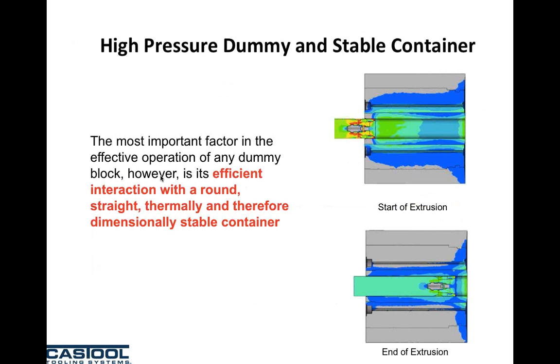What we are trying to achieve, through a high pressure dummy block and a stable container bore, is an efficient interaction of the container, liner, and dummy block. So when you start to push, the active clearance between the liner bore and the dummy block is consistent, and when you retract, the dummy block is not yielding and the nominal stays the same, so you can retract and leave the skin, not touching or dragging the aluminum skin out of the dummy block or out of the liner bore as well.